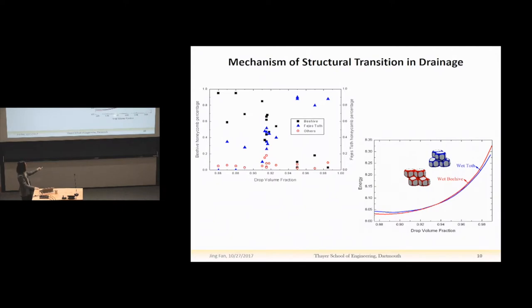And we found that when the drop volume fraction is below about 0.935, the beehive is energy favorable. And when the drop volume fraction is above 0.935, FT honeycomb is favorable. So they're roughly consistent with each other, the theoretical prediction based on an equilibrium system with our experiments.